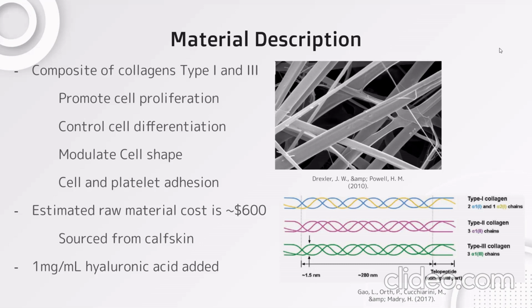We source the materials from calfskin, since it has both type 1 and type 3 collagen, albeit type 3 in lower concentrations, and is also readily available on the market. So in past studies, 1 milligram per milliliter concentration of hyaluronic acid mixed into collagen has been shown to give the collagen boosted anti-inflammatory properties. So we do this before we go on to the next step in the process, which is electrospinning.